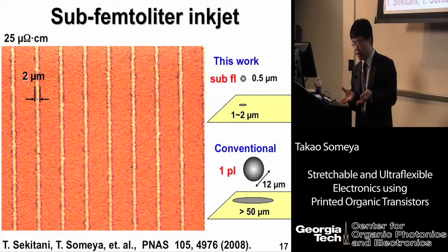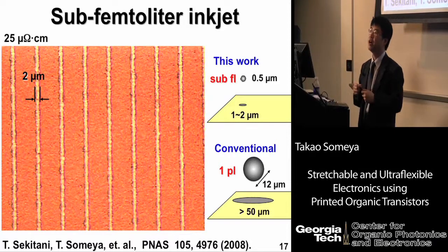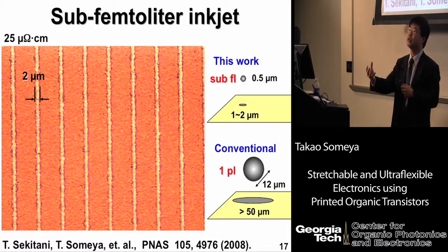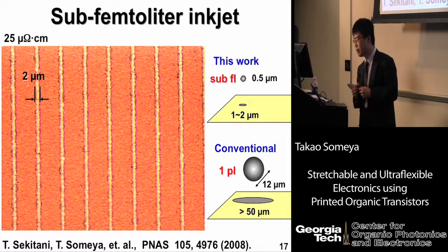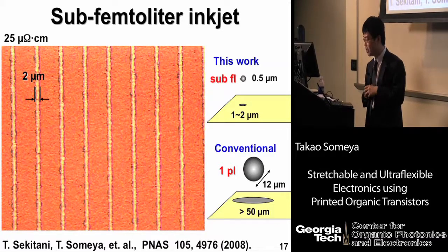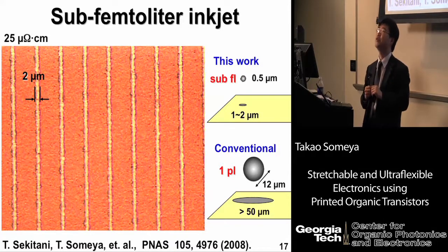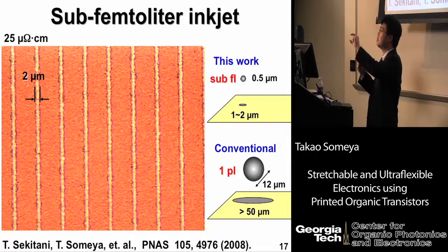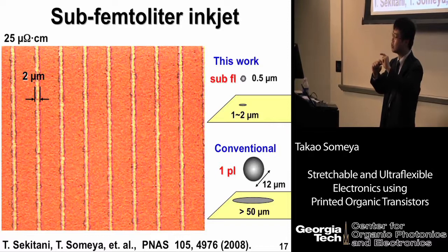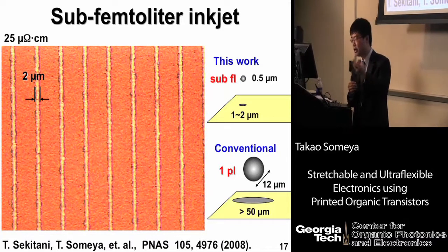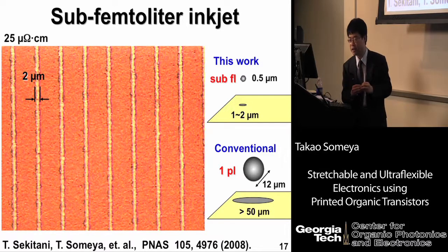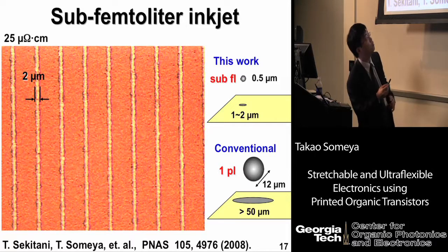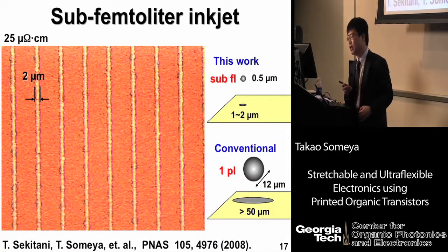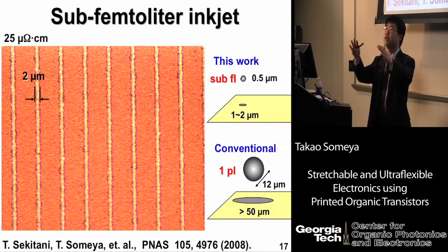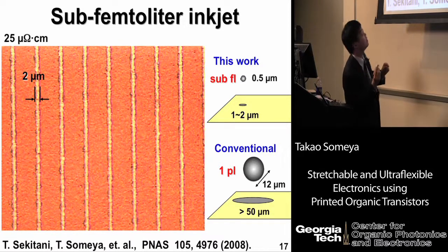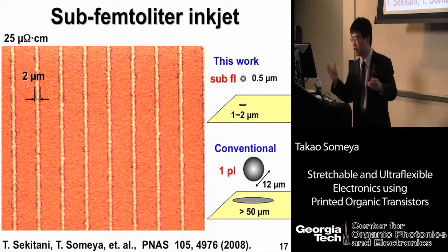In order to apply the printing processes for active device application, one of the major concerns is spatial resolution. And here is a new development. The typical conventional inkjet can control the tiny droplet with accuracy of 1 picoliter. But now we apply the external field between the tip of the inkjet nozzle and the substrate. And now we can control the droplet precisely in the sub-femtoliter accuracy, which corresponds to 0.5 micron in diameter. So by using the novel sub-femtoliter inkjet, now we can write extraordinarily fine patterns, something like that, in a resolution of 1 or 2 micron on any kind of substrate.